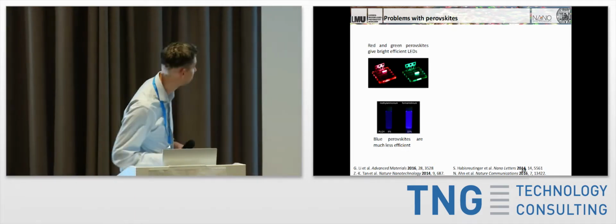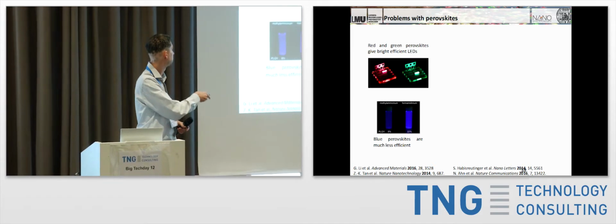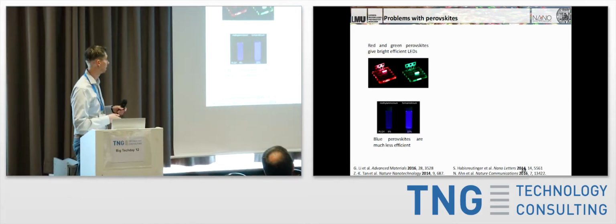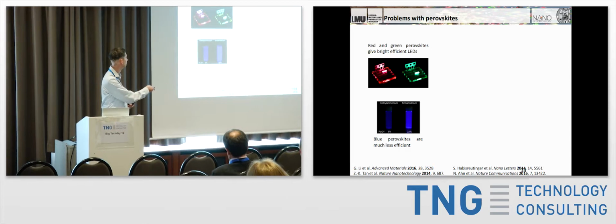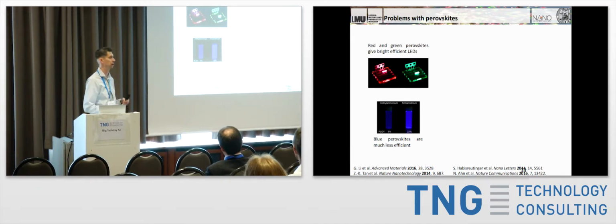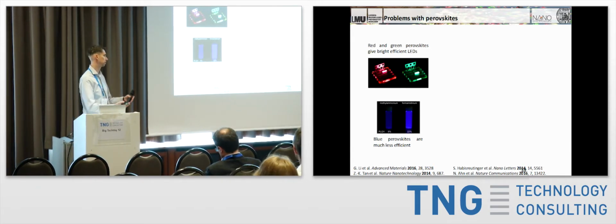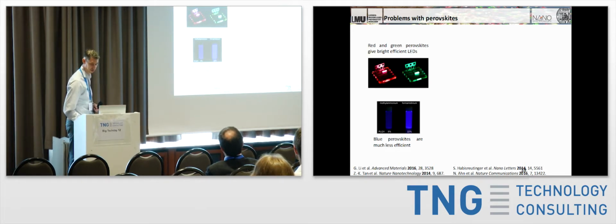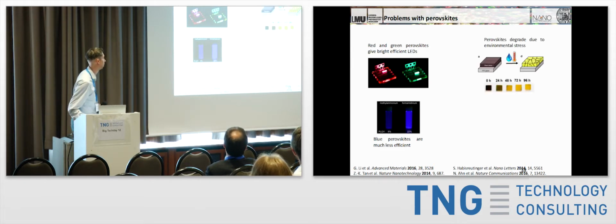So this is essentially just two dispersions of blue perovskite nanocrystals in there, and you can see the quantum yields are only about 6 and 22%, so that means the amount of photons absorbed by the light and then actually producing blue photons. So it's a lot less efficient. And so obviously if you want to have an all perovskite LED, you'd like to have blue, green, and red coming together. Another big problem is environmental stress.